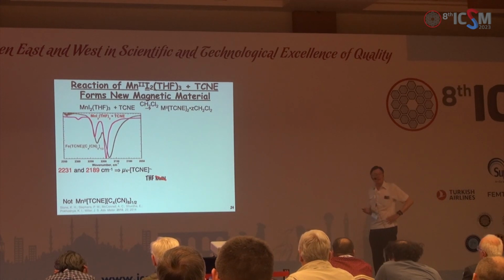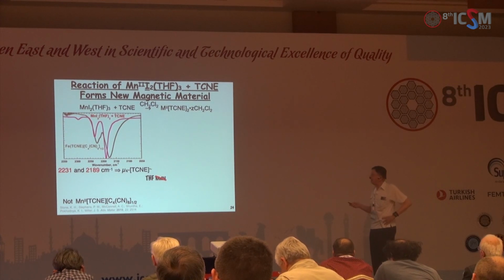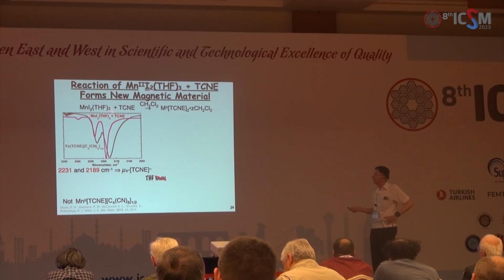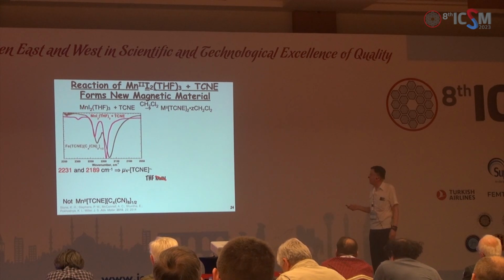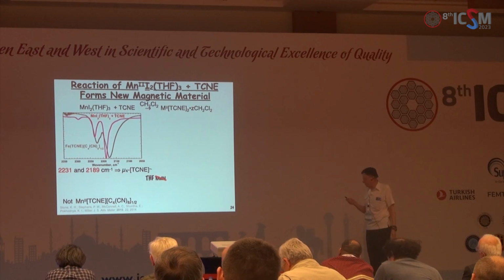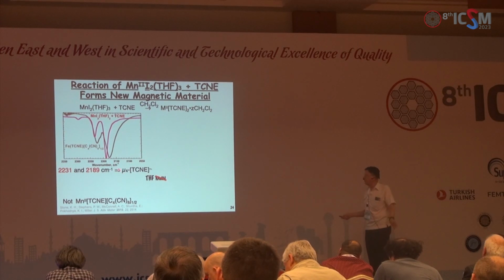I'm going to stay with the manganese, stay with TCNE, stay with the iodide I talked about, but change the solvent from acetonitrile to THF. There's only 3 THFs per manganese, basically the same as in acetonitrile, but we're doing the same chemistry, and I'm going to show you 2 different infrared spectra—not important, except they're different.